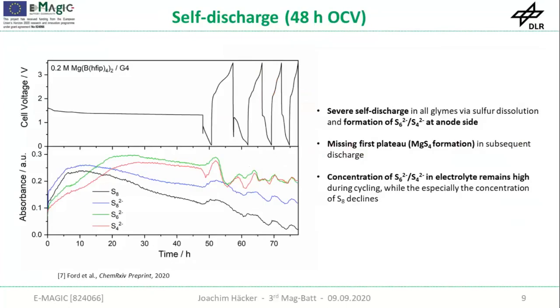If we have a look at the self-discharge, so the behavior during OCV, severe self-discharge is observed in all glymes we examined, with a high initial elemental sulfur and S8 2- concentration. And after around 20 hours, the short chain polysulfides take over, so they are formed at the anode side and are then dominant in the electrolyte solution.